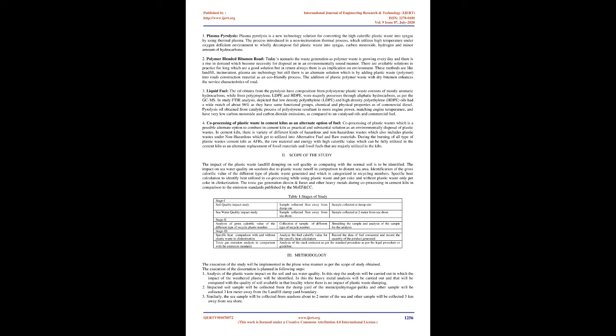3. Liquid fuel. The oil obtained from pyrolysis has a composition dependent on the plastic. Polystyrene plastic waste consists mostly of aromatic hydrocarbons, while polypropylene, LDPE, and HDPE mostly possess aliphatic hydrocarbons, as per GC-MS. In a study, FTIR analysis depicted that low-density polyethylene, LDPE, and high-density polyethylene, HDPE, oils had a wide match of about 96% as they have the same functional groups, chemical and physical properties as commercial diesel. Pyrolysis oil obtained from the catalytic process of polystyrene resulted in more engine power, matching engine temperature, and very low carbon monoxide and carbon dioxide emissions, as compared to uncatalyzed oils and commercial fuel.